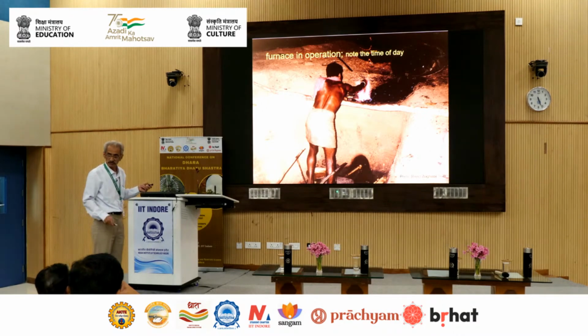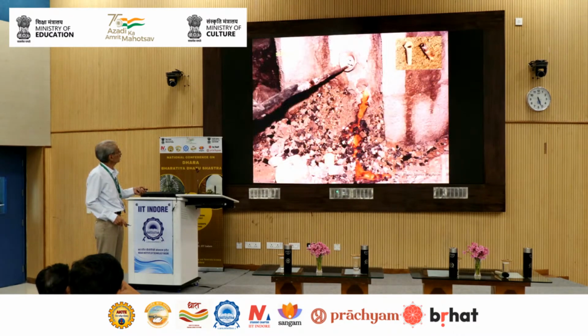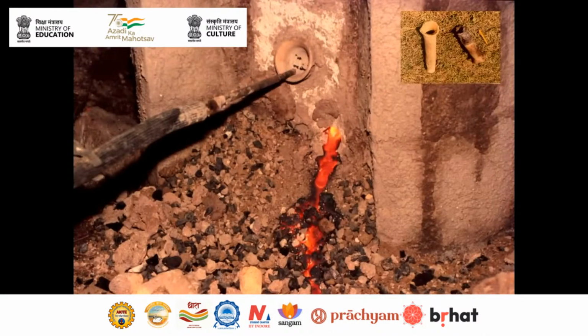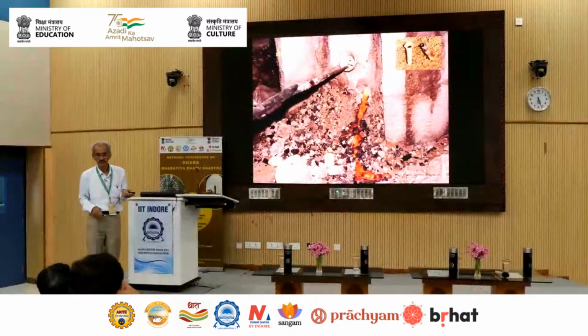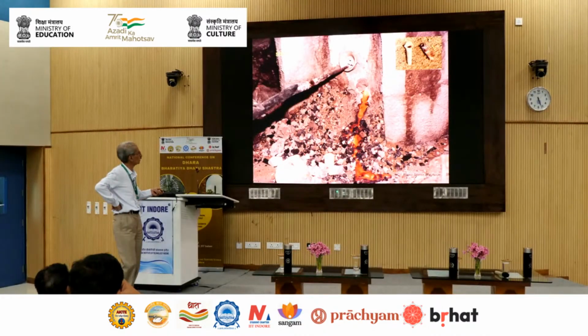And that's how it is always done. And halfway through he'll start doing slag off. The slag has to flow, and this is the quality control. If they see the slag of the right type, not too much, but lack of slag means iron is not going to be produced. So slag has to flow out to some extent.